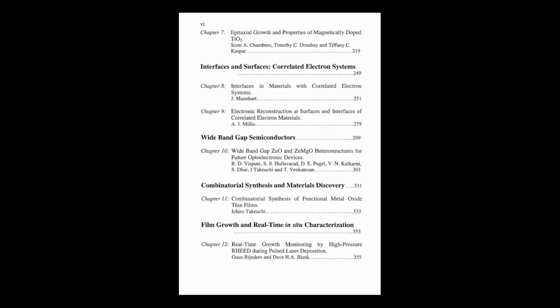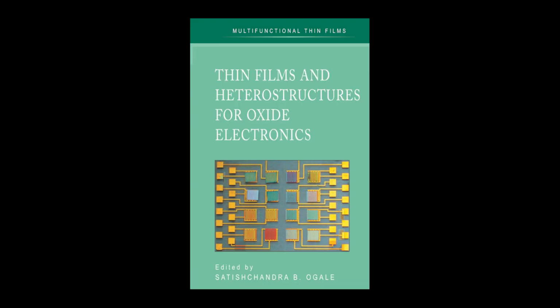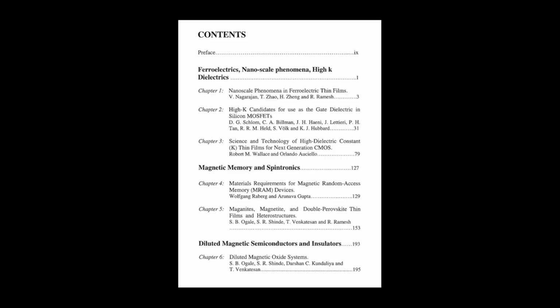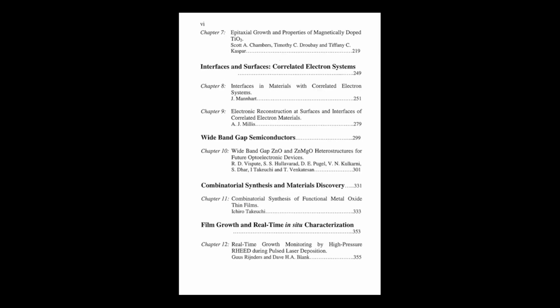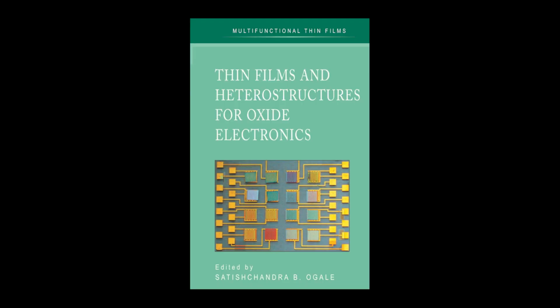But the really nasty surprise, the one that caused major problems once HfO2 was actually being put into production, was mobility degradation. Yes, that was a big one. It sounds totally backward. You replace a leaky insulator with a better one, and suddenly the electrons in the channel underneath move slower. Why? It's one of those classic unintended consequences tied directly to why these materials have high K in the first place. They rely on having soft metal-oxygen bonds. Bonds that are easily polarized by an electric field. That's what gives them high K.